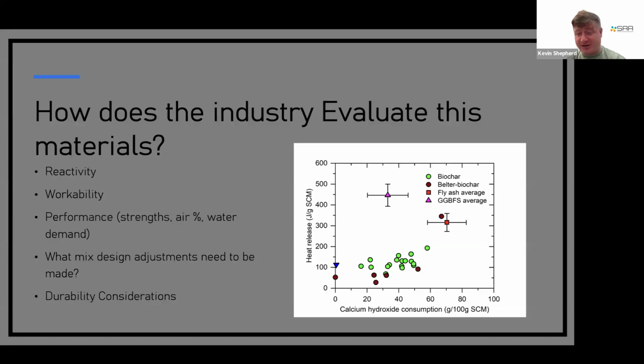So when we started actually looking at how it flows, looking at the slump, looking at how you could use a steel trowel against it, we noticed there were some issues that would narrow down your applications. We look at the performances, of course: the strength, the air percentage, the water demand. I'm only saying that because that's what we see the biochars affect. If you don't modify your mix design, your strengths aren't going to reach the appropriate benchmarks. You're always going to add a little bit of air unless there's some type of treatment you could use. And your water demand is always going to go higher from what we're learning right now.